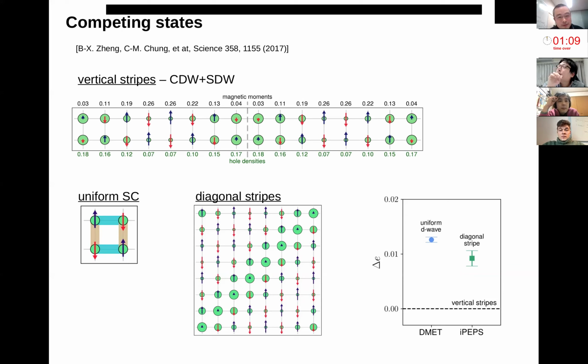The first thing is that with negative t-prime and with higher doping, we see almost a superconducting state, and then the hole density is pretty uniform. So it's not like a strong stripe state here. And also the spin expectation value is very small. So in order to see this kind of stripe behind the state, we need to apply a magnetic field on only one of the edges. Then we can see that the spin responds all through the bulk. And from there, we can see that when you apply the pairing field, the stripe order can change from the commensurate to the incommensurate.